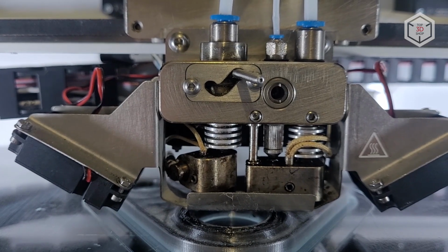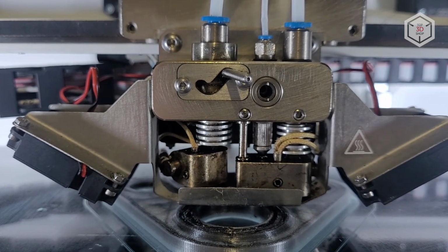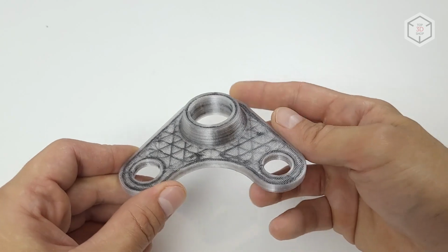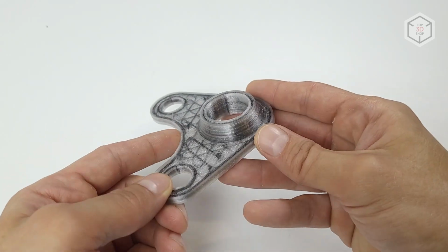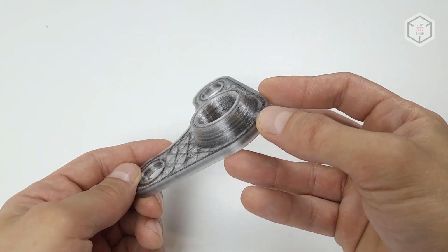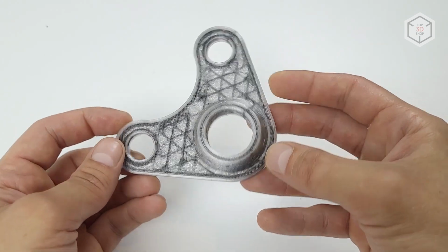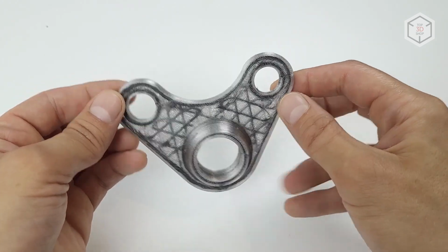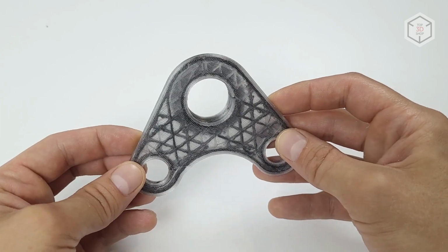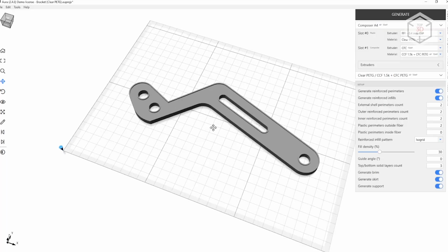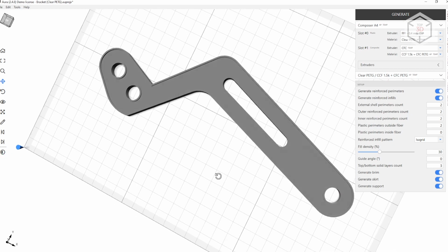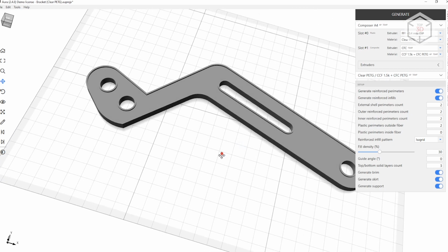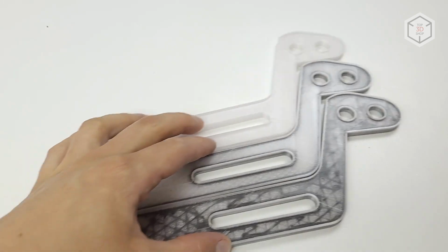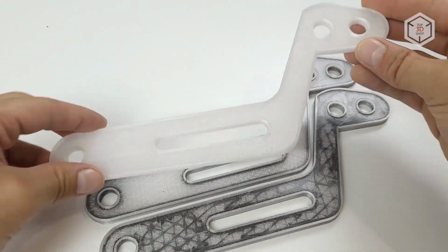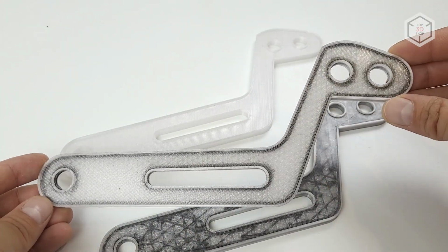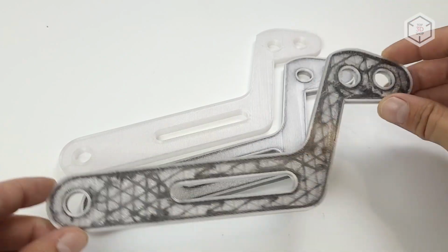Besides, when printing the reinforced contours, fiber particles sometimes got on the plastic perimeters, leaving small black dots on the surface. We do not have any complaints about the plastic extruder, as it did everything right, though not fast. Overall, the part turned out pretty good. Might be not as neat as shown on the website and in the brochures, but for the first test, it was okay. For the second test, we modeled a non-complex part to print it in 3 ways. It is a kind of lever with holes and a notch. In the first version, we printed it with PETG only, and in the second version, we added reinforced contours. For the third time, we used both reinforced contours and reinforced infill.